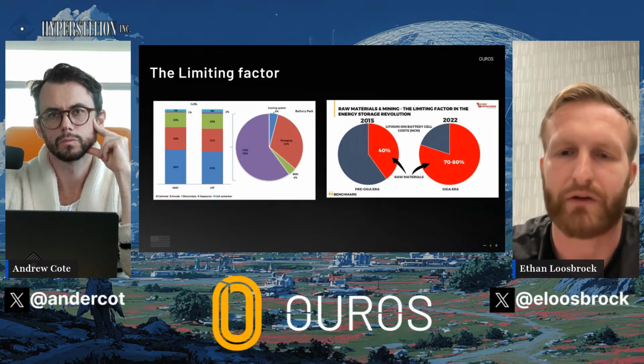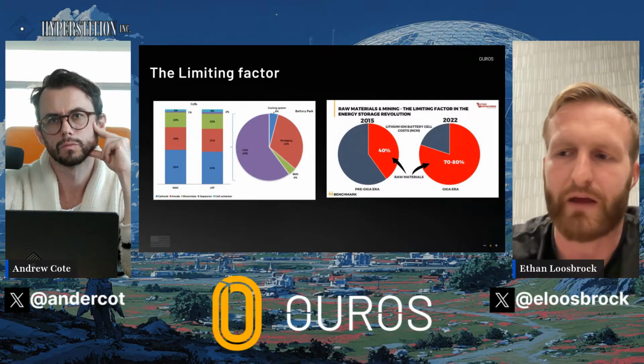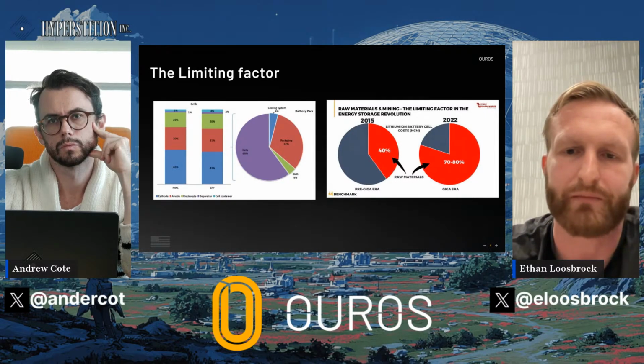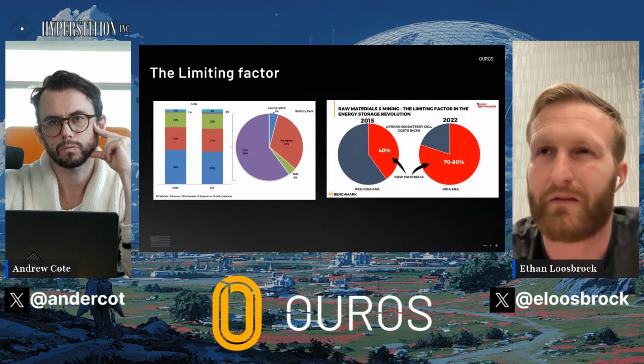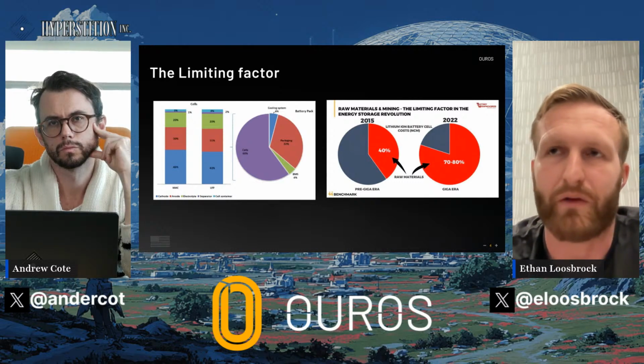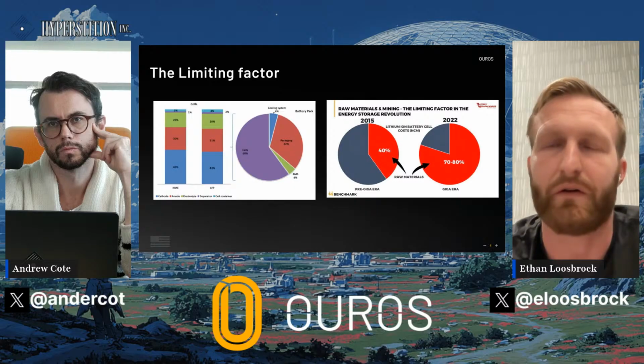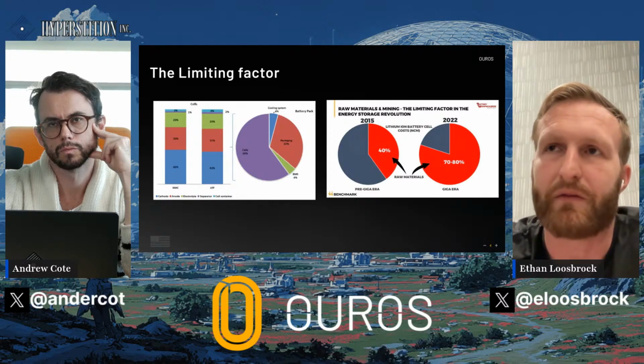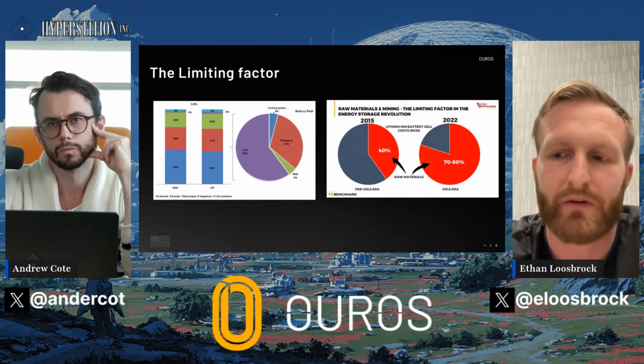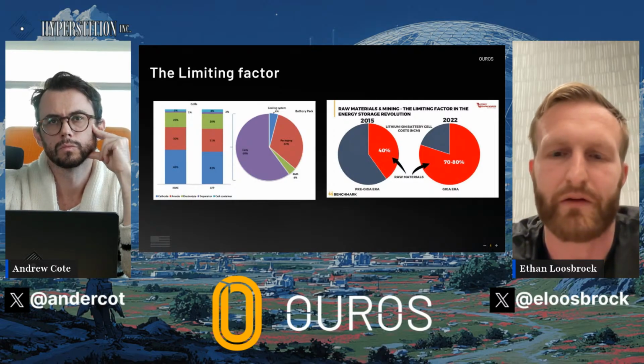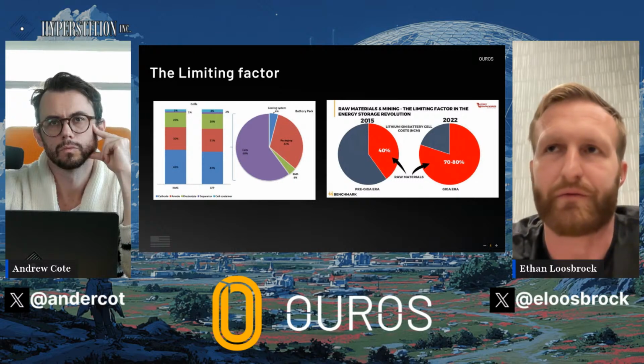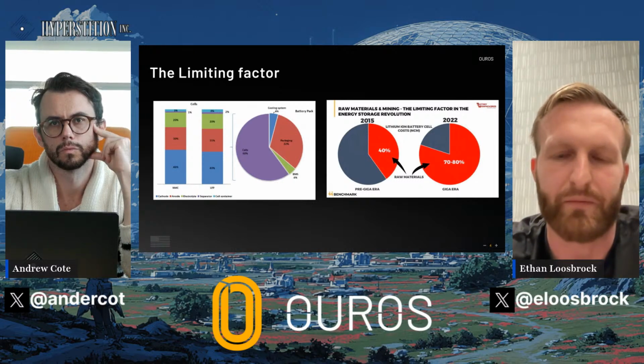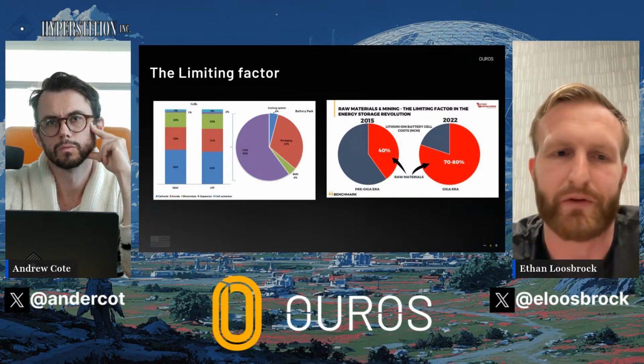So they combine the hydroxide or carbonate with, if it's NMC, nickel, manganese, and cobalt sulfates. If it's LFP, there's a variety of different methods people are using right now, but you somehow combine it with a phosphate compound and an iron. Sometimes it's phosphoric acid, but people are changing that process quite a bit right now. The hard rock is lithium carbonate that's in rocks, primarily from Australia. You crush the rocks and leach it, but ultimately you produce a lithium carbonate. That process typically doesn't produce hydroxide.